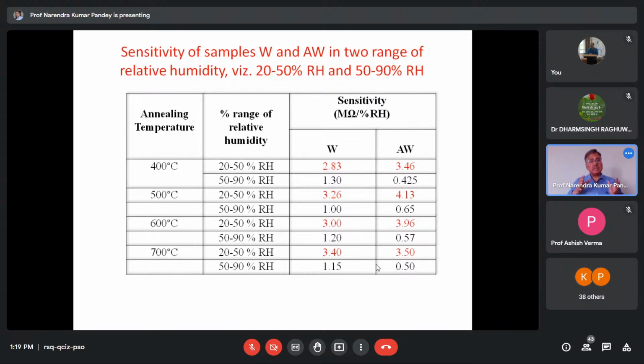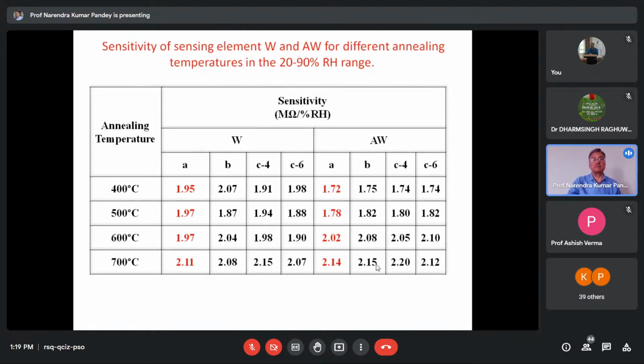But mind you, the role of annealing temperature is also very important, because at lower annealing temperatures the changes in sensitivity are not much, but when you go to higher annealing temperatures, the change is very large. Sensitivity increases very much. You can see from here that this is for the pure WO3 that we have, and this is for silver doped WO3.